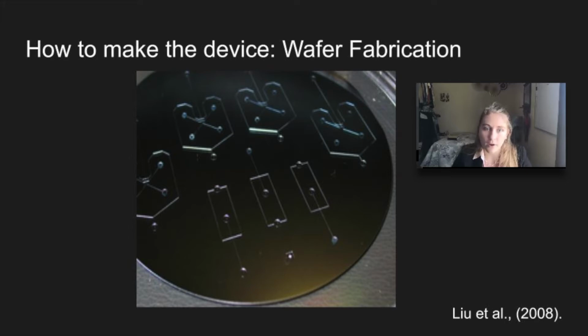Once the silicon wafer is cleaned, the photoresist is placed on the wafer, and the wafer is placed in a spin coater apparatus. The spin coater ensures an even coating of the photoresist across the surface of the wafer. After that, the wafer is heated by ramping for a slow evaporation of the solvent, which helps to ensure that the other chemicals can spread more evenly on the surface of the wafer. The wafer is now ready to be imprinted with the device design. The wafer is placed under UV light and exposed for a time determined by exposure energy divided by the light intensity, with the mask on top of the wafer.